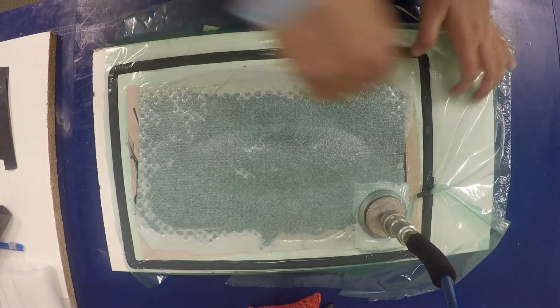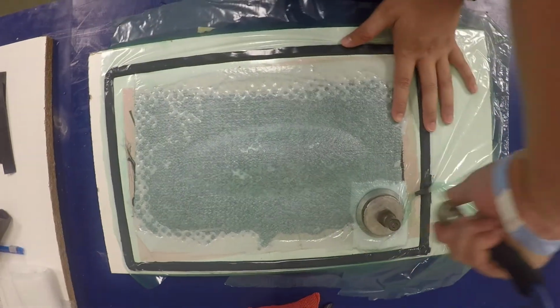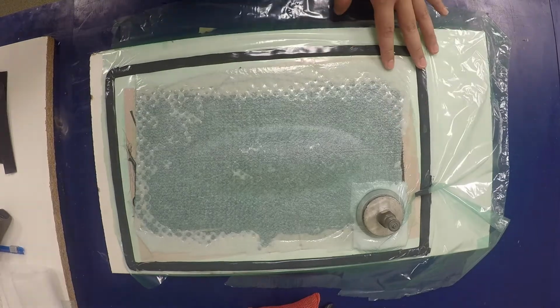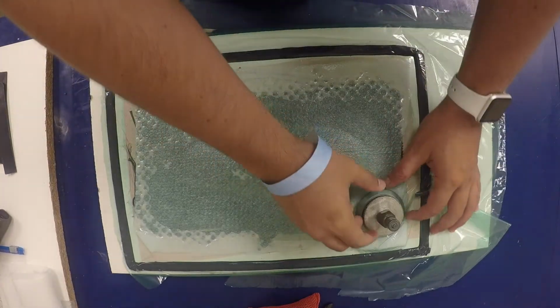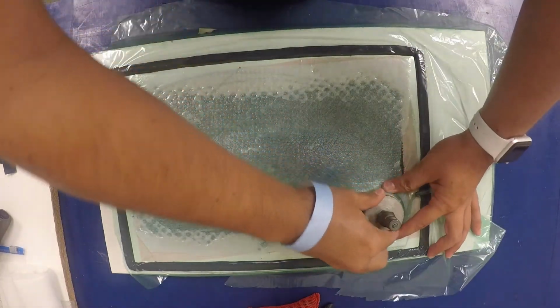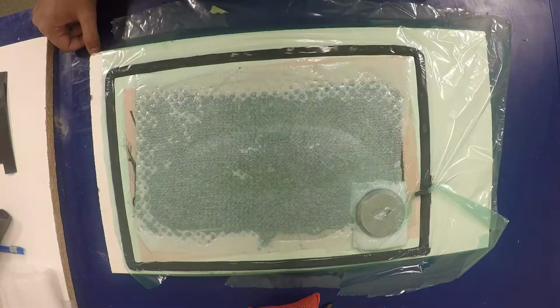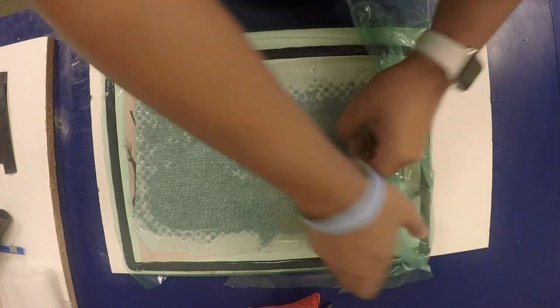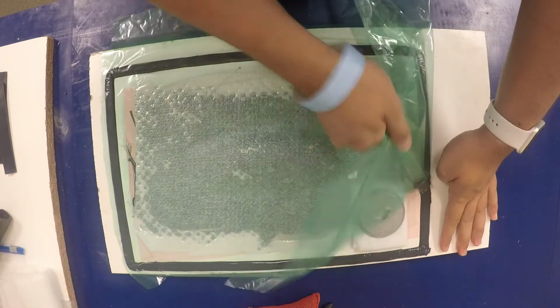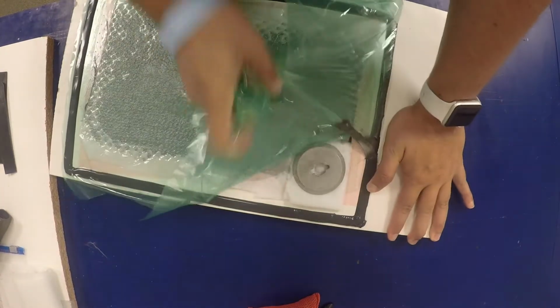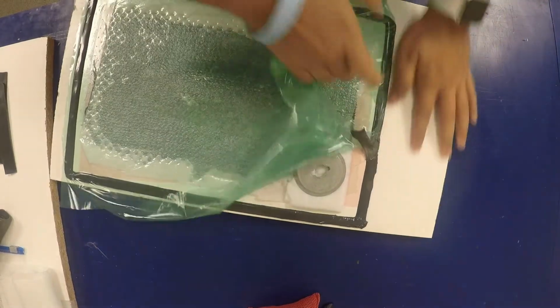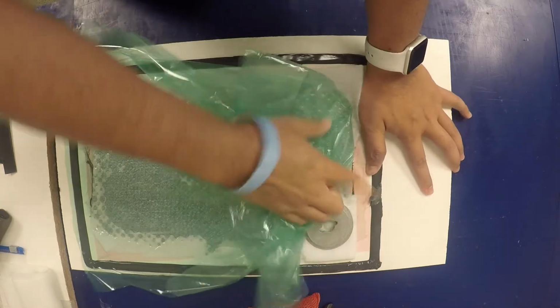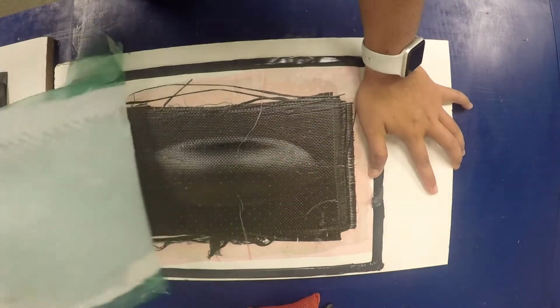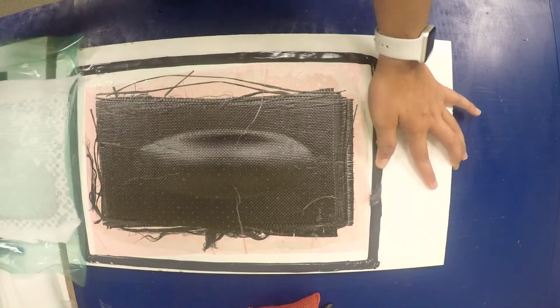After leaving your component to complete its cure cycle, you can unbag the final product. To begin, you must first disconnect the vacuum hose and remove the top portion of the vacuum port. You can then proceed to remove the vacuum bag. Do this by firmly tugging on the vacuum bag to unstick it from the tape. It doesn't matter if the tape stays stuck to the bag or to the mold. Most often, the bleeder will adhere itself to the vacuum bag and will also peel off from the final product.